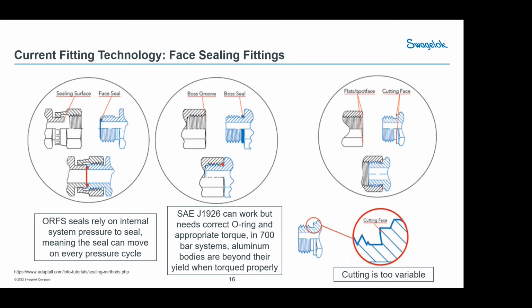By the time you got a gap of a small amount, the O-ring would then squirt out through that gap. And that takes about 1,000 cycles, by the way, and we've heard that from the test houses as well. When they fail, they always fail between 1,000 and 2,000 impulse cycles. So how to prevent that is making sure that you're not too close to the limits on what the fitting design is. On 1926, there are two different designs. There's a light duty and a heavy duty.